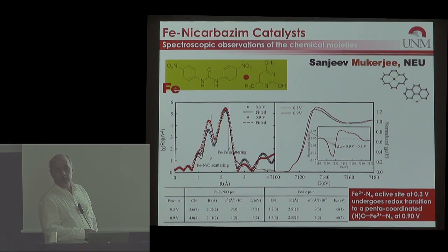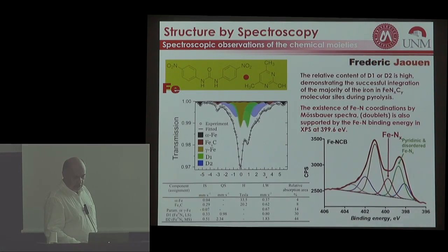This catalyst actually is more heterogeneous than the one described before. It does have iron-nitrogen types of species, but it also has iron-iron species, as shown here in the EXAFS and XANES spectra. Also, Frederic was kind enough to provide the Mössbauer spectra of this catalyst that, in addition to the two doublets that were discussed, D1 and D2, shows gamma iron and alpha iron and also iron carbide. So it is more heterogeneous as a material, which can also be confirmed by the complexity of the XPS nitrogen spectra.